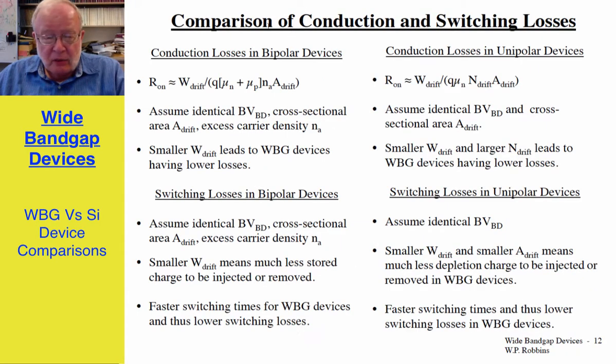If we can make a qualitative comparison between conduction and switching losses, conduction losses in bipolar devices are dominated by the on-state resistance, and if we assume identical devices, that is breakdown voltage, cross-sectional area, and excess carrier density, the smaller drift region length means that the wide bandgap device is going to have lower losses. In bipolar devices, switching losses are also going to be much less in the wide bandgap device because of the much faster switching time.